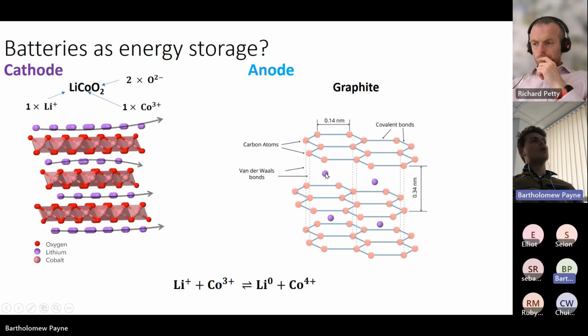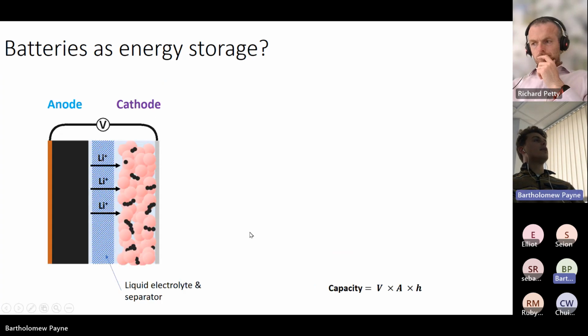And this is almost as if it's lithium metal, so Li0. It's slightly stabilized, but it's almost as if it is. So then we get this redox reaction here. On one side, we've got Li1+ and cobalt 3+, and then you reduce the lithium ions to lithium metal and oxidize the cobalt cations. Schematically, what this looks like in a real cell is you move your lithium from the cathode to the anode and it's charged, and on discharge, you move your lithium ions from the anode through to the cathode, and your electrons will move around the circuit.